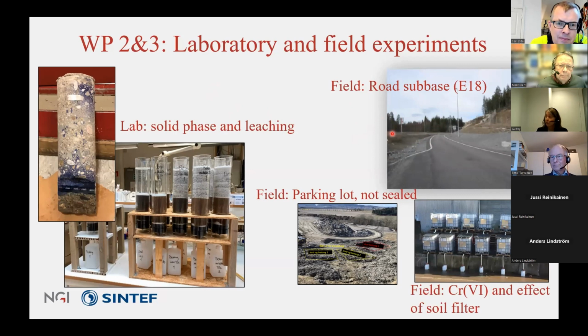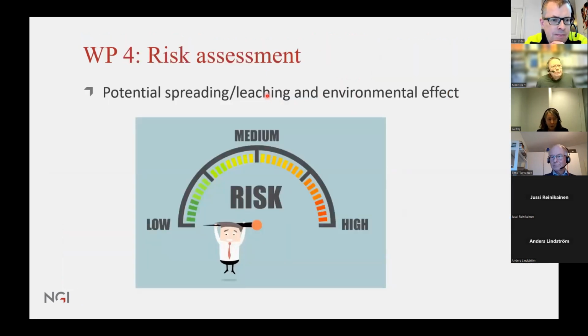So they had a lot of data on the leaching of concrete, or chromium, not chromium-6, but they continued in this project analyzing for chromium-6 also. And here they had used waste concrete as a part of the road. We had a parking lot, or we were imitating a parking lot without asphalt. And we also had some container tests at Lindum landfill site. So there were several user partners part of this, contributing test sites, which is of course of great interest. But just to focus on the risk assessment of chromium-6 in